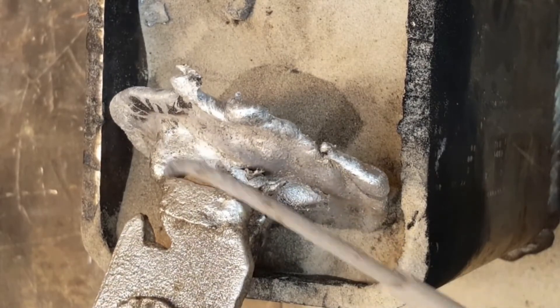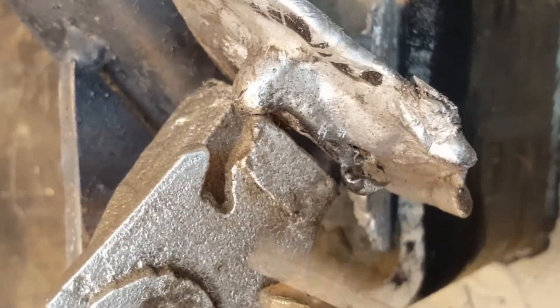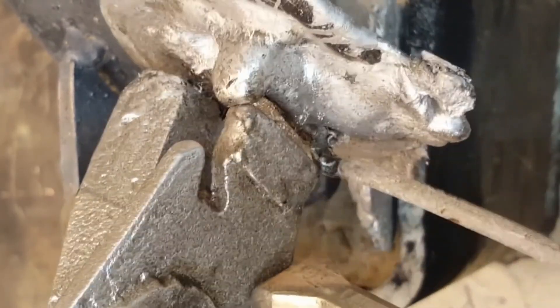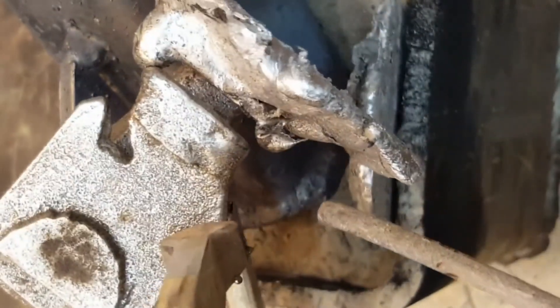The problem is the top side — this is where it didn't go in. These little bits here — that's tough. On further review, you can see that the mold filled from this one and started to fill up here but solidified, then didn't weld together when I pushed it over and tried to get it to fill the other section. So it's this thin section that's killing us. Clearly if we can't get thin, we're gonna have to get thick.